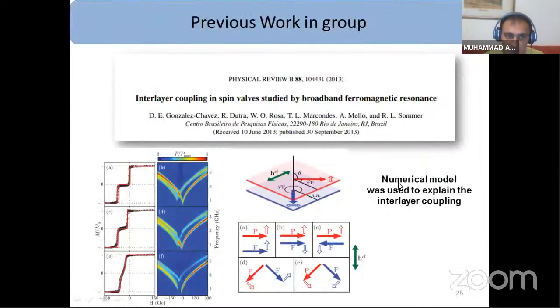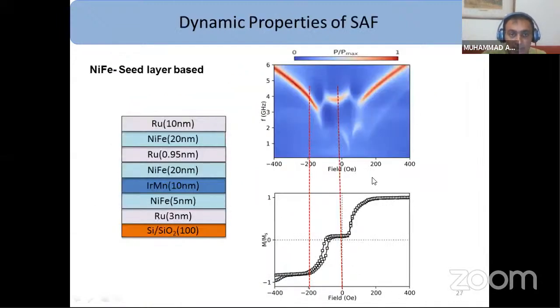We have already done work on interlayer coupling in spin valves studied by VNA FMR. You can see we have our own numeric model to explain the interlayer coupling, and by using this model we can also extract anisotropies in our system. Here this is a synthetic antiferromagnet with a seed layer based system. You can see the respective dynamic modes, oscillation modes, with respect to the antiferromagnetically coupled region and this region.